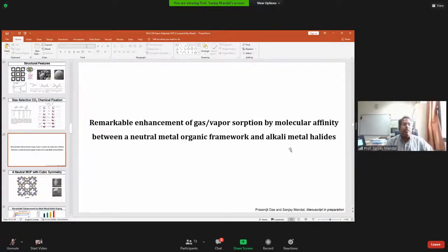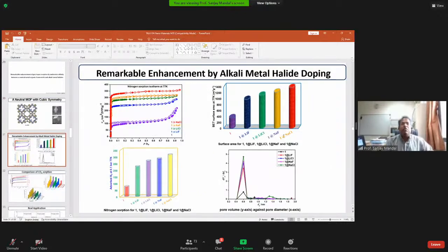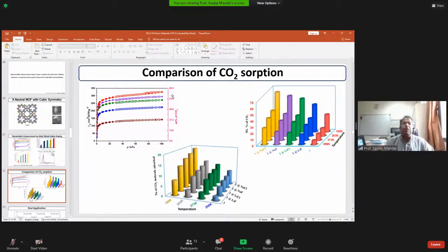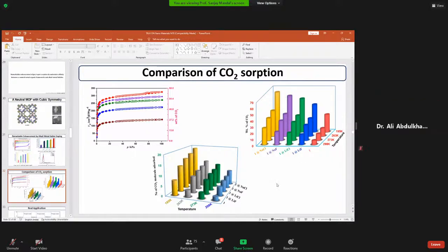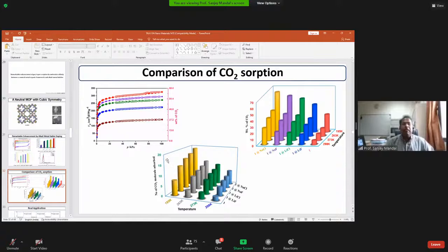The last one, which is not published, but I can share a little bit, is a cubic crystal. Here what we have done is dope the MOF with halides: sodium chloride, lithium chloride. And we find that sodium chloride, table salt, increases your surface area from 400 all the way to 1400. What is important to note here is that the pore size is the same, but the pore volume goes to 4.75, which I mentioned earlier in my talk. If I dope the MOF with halides, sodium chloride, I get an increase in the weight percent of CO2 from 27 to 67. Here you can see the weight percent of CO2 versus temperature, because at higher temperature you have less adsorption, right? Sodium chloride gives you about 19 molecules there.